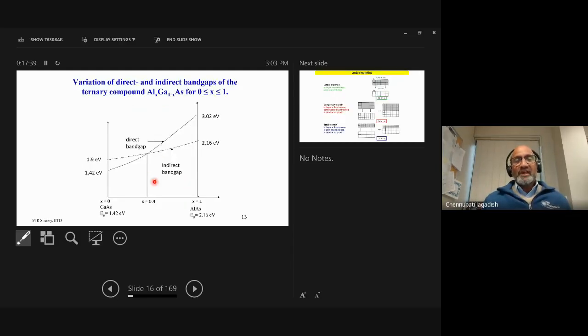So here is an example of the case I was mentioning, by mixing the materials, so-called alloy semiconductors, you'll be able to tune the band gap. You can see that gallium arsenide is here, aluminum arsenide is here, and the direct band gap of the semiconductor is plotted here. In the gallium arsenide case, direct band gap means the maximum in the valence band and the minimum in the conduction band happen at the same wave vector, and that means this is a direct band gap here, for example.